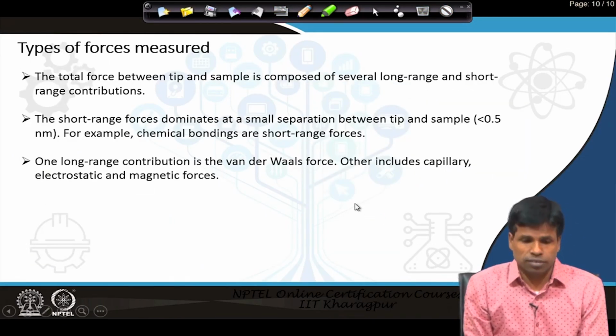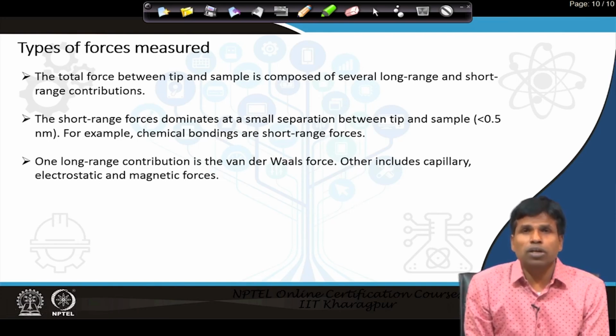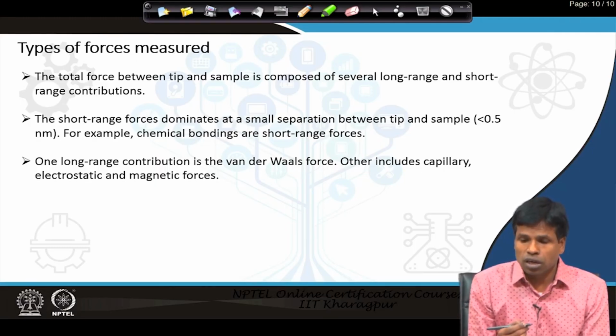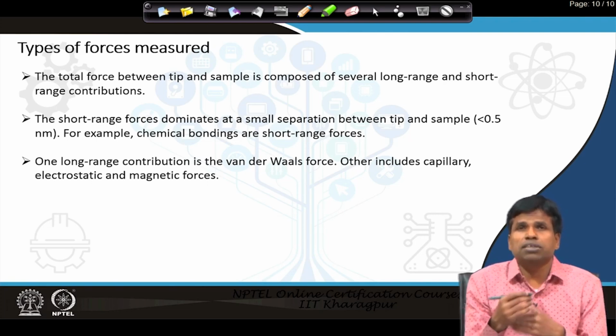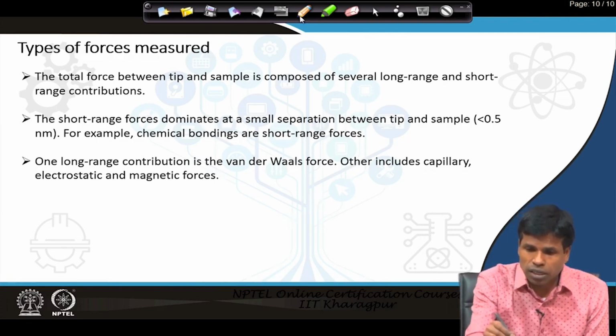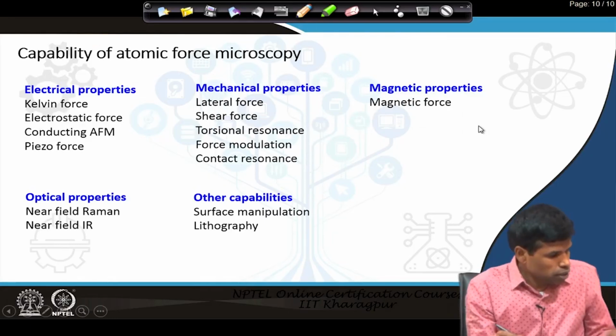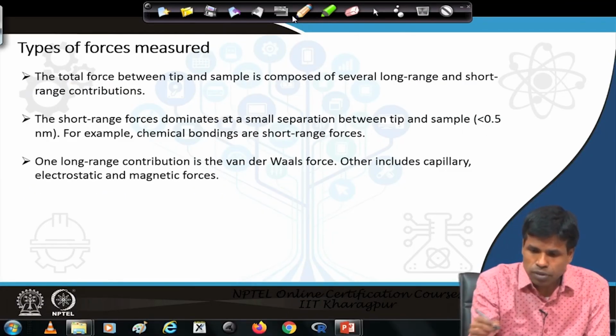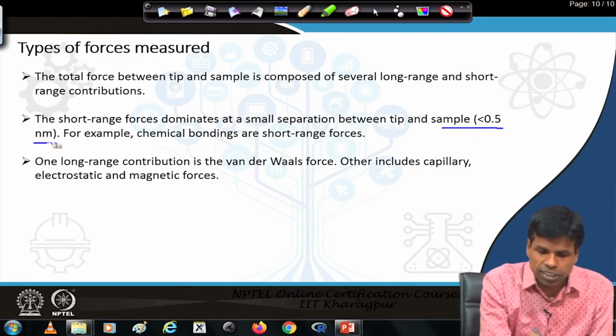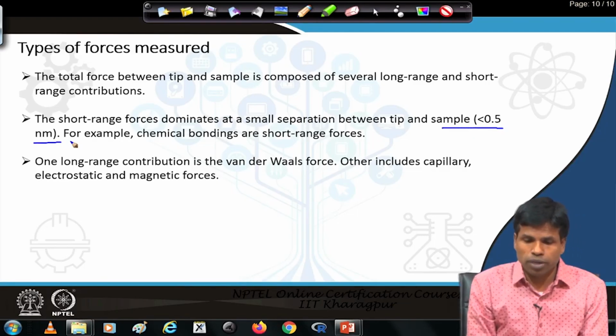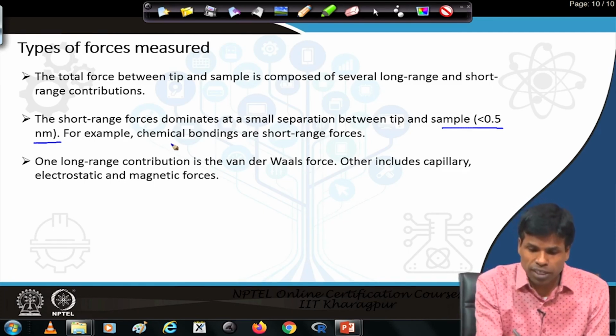So, there are different forces. The total force between the sample is composed of several long range and short range forces. Short range forces include chemical bonds, different types of bonds, and the short range forces are there when the tip and sample are less than 0.5 nanometer apart. When the distance between the tip and sample is less than 0.5 nanometer, there will be short range forces such as chemical bonding etc.